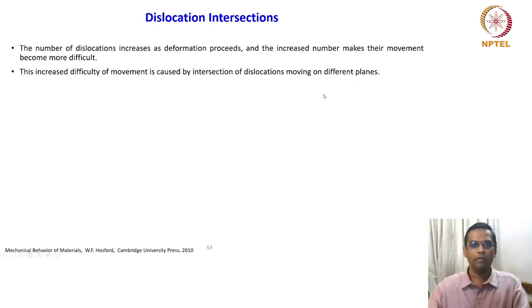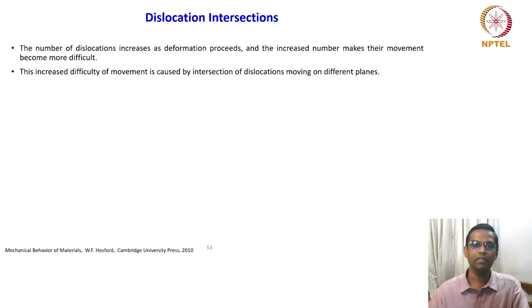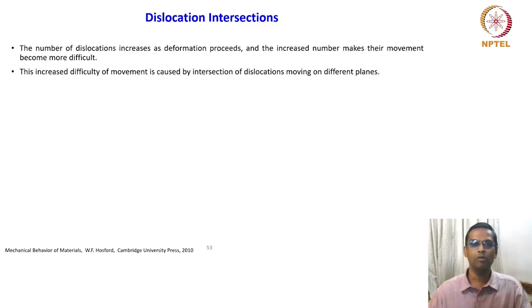We were talking about dislocation cross-slip and the interaction of one dislocation with another. All these things will have some impact on dislocation density. I also mentioned about wavy slip and planar slip, where in a wavy slip material we are connecting the mobility of dislocation in three dimensions — the dislocation motion is not restricted to a given plane, unlike in a planar slip material.